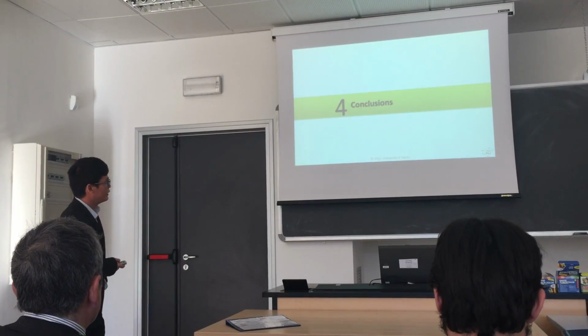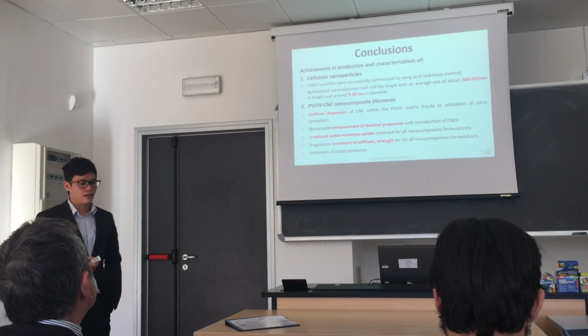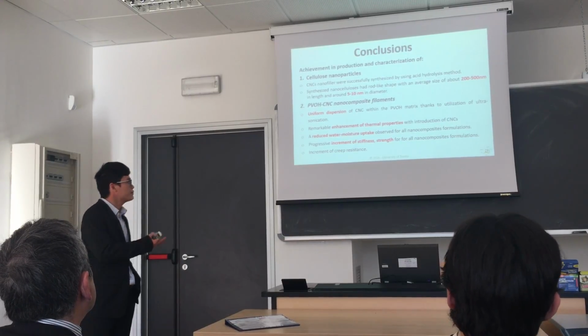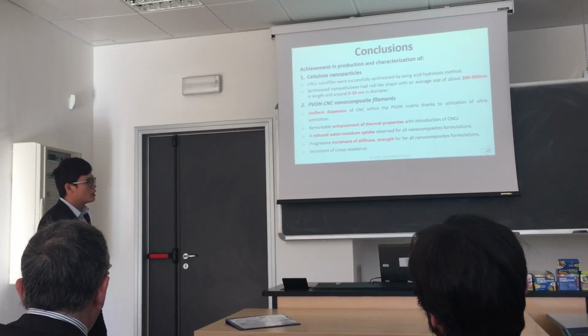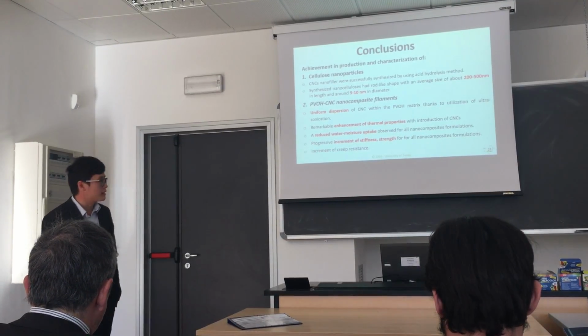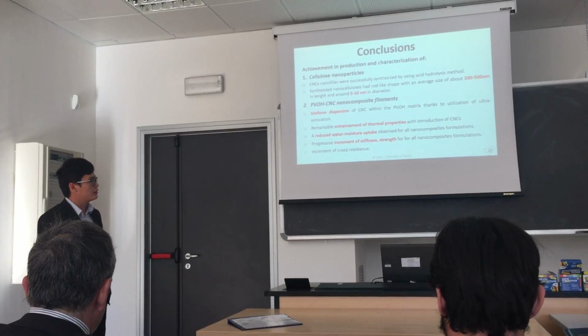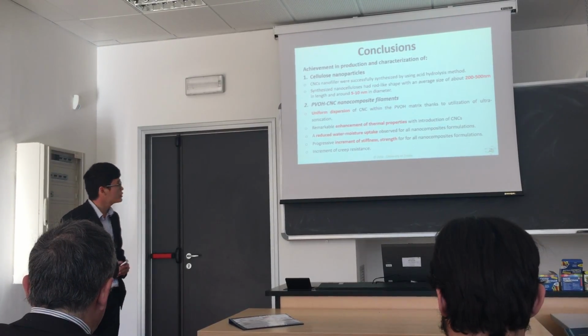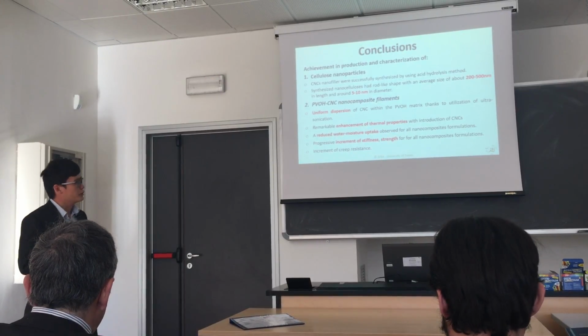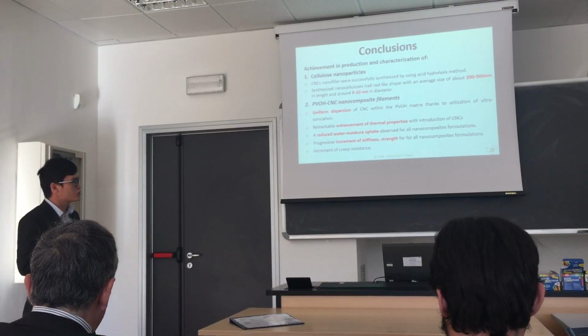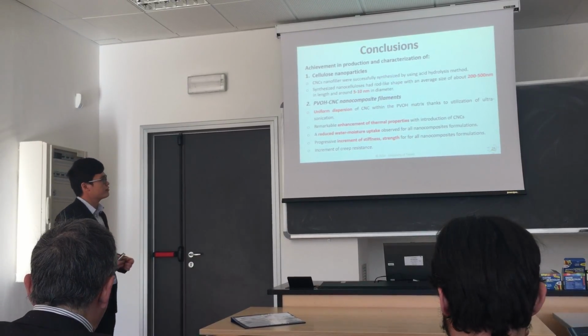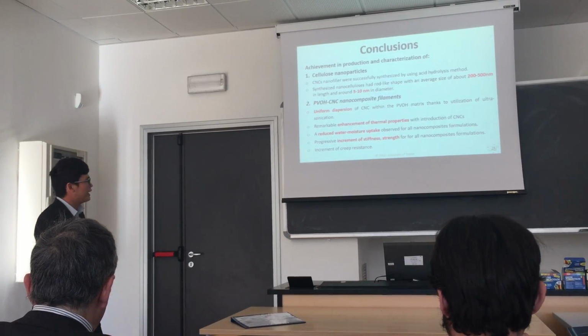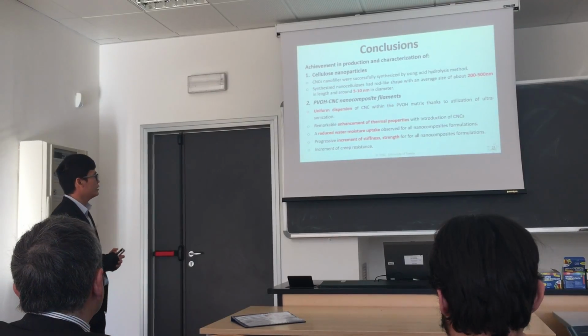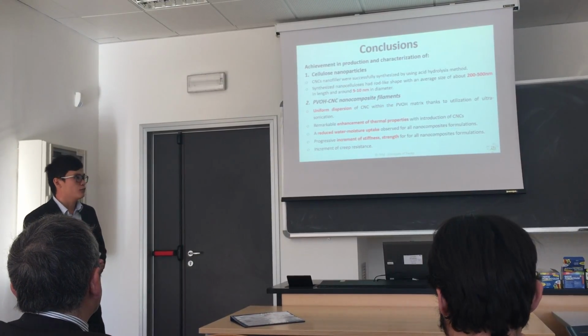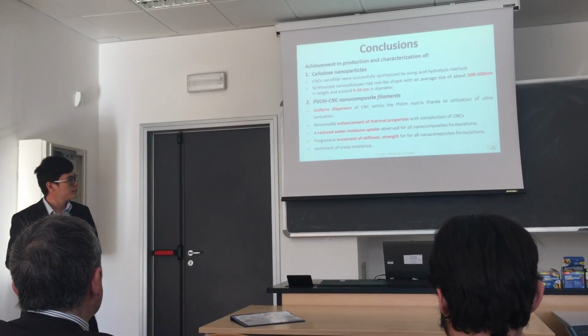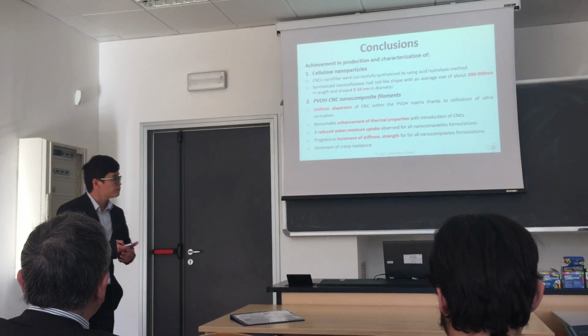So let's come to the final part, the conclusion. My thesis has successfully achieved three main parts. The first part relates to the production and isolation of nanocellulose, a nanomaterial that I synthesized. They are rod-like, with an average length between 200 and 500 nanometers and a width of around 5 to 10 nanometers. We also succeeded in producing the nanocomposite filaments through the application of ultrasonication, and the introduction of the nanocellulose gave good properties in terms of water vapor resistance and an increment of the stiffness, the strength, and also the creep resistance.